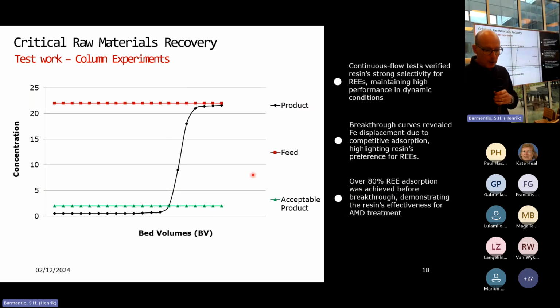So we wanted to see what would happen. Our test work looks at things like bed volumes and breakthrough curves. If you don't know what a breakthrough curve is, basically it's telling you after how many volumes, which is the amount of liquid that's flowed through the system, how long does it take before you start seeing your inlet equal to your outlet. So that's where you start getting breakthrough, and your exhaustion is at that point. That's when your inlet is equal to your outlet, so nothing's really happening in your resins.